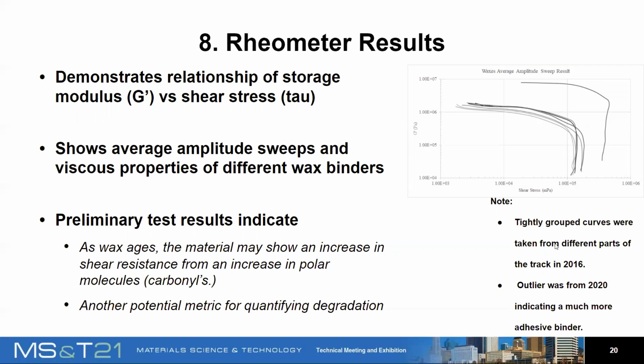a track in 2016. And the one that's more out here, which is away from the clumped sweeps, was taken in 2020. So you can really see how, after 4 years, there is a difference in the shear stress and the G prime results. And as the wax ages, it shows an increase in the shear resistance, which increases the polar molecules. This just shows another way of quantifying the degradation of our material.